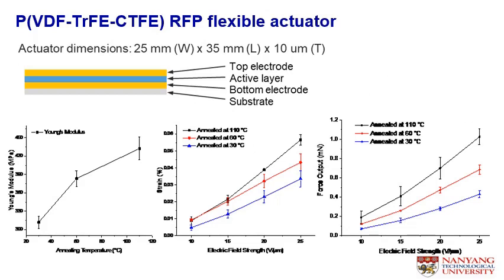In the fabrication of the actuator, the top-bottom electrode is sandwiching the active terpolymer layer that has been annealed at various temperatures. Due to the crystallization behavior, as shown here, when it's annealed at 110 degrees Celsius, the device is giving us the highest strain and highest output force as a function of electric field strength. This corresponds to the improved Young's modulus due to the crystallization of the terpolymer.